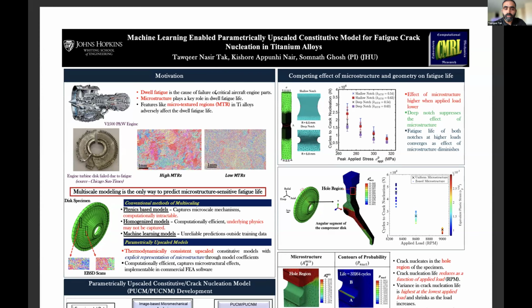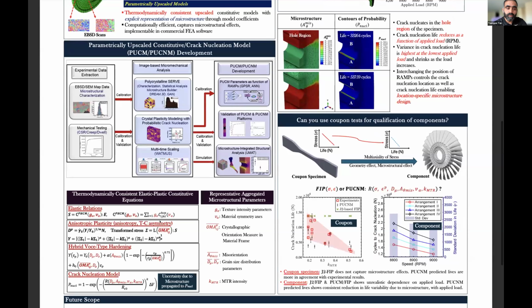So what are these parametric upscaled constitutive crack nucleation models? These have three modules. The first one is experimental data, where we get the experimental data and then do the mechanical testing. We use this data in our second module, where we develop the crystal plasticity based micromechanical models for grain scale crack nucleation prediction. And then we generate the database using these micromechanical models and develop the upscaled models that have the dependence on the underlying microstructure. Now, as we can see from here, these are the equations that represent the model.